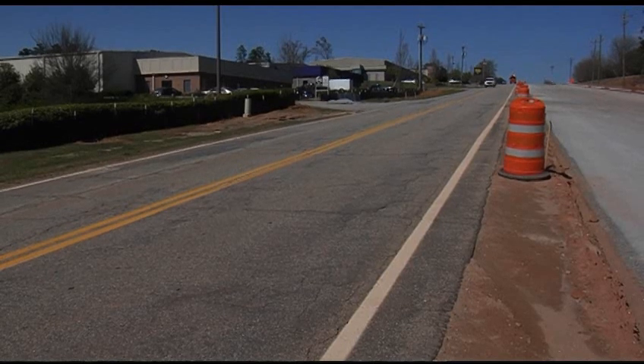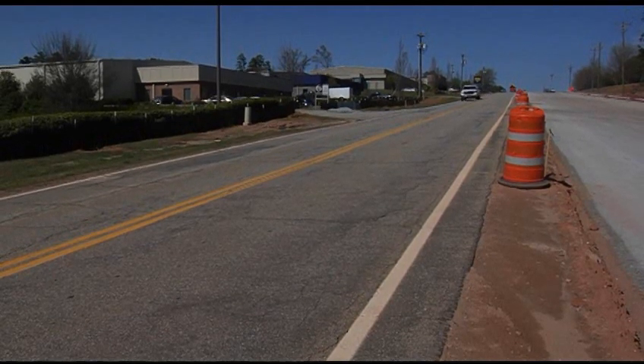On Richland Avenue in Aiken, South Carolina, the project consisted of removing 10 inches of existing pavement and immediately placing 10 inches of roller compacted concrete in one lift. The project was four lanes wide and a mile long, and including diamond grinding the surface, the entire project was completed in 15 days — ending with a ride comparable to new interstate pavement, despite matching an existing curb and gutter. This was faster than the estimated 33 days had it been an asphalt road.